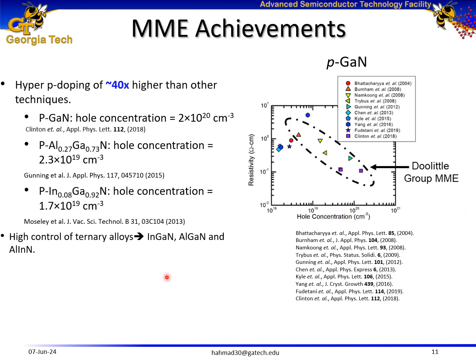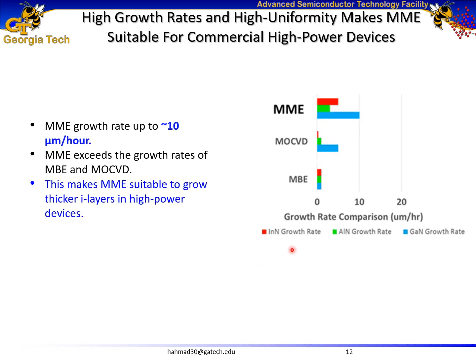Some of the major achievements of metal modulated epitaxy include hyper p-type doping approximately 40 times higher as compared to the other growth techniques for gallium nitride, aluminum gallium nitride, and indium gallium nitride. It also achieves high control of ternary alloys. Furthermore, MME achieves a growth rate up to approximately 10 microns per hour, which exceeds the growth rates of both MOCVD and MBE. This makes MME suitable to grow thicker i-layers in high power devices, which is the field that I want to pursue.